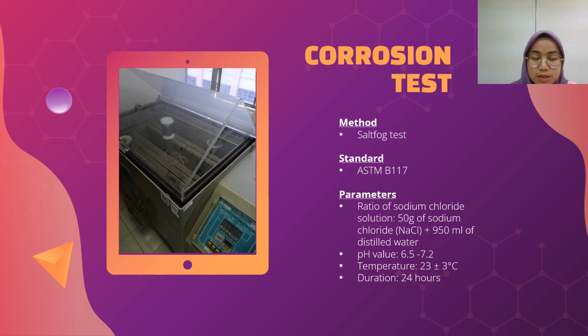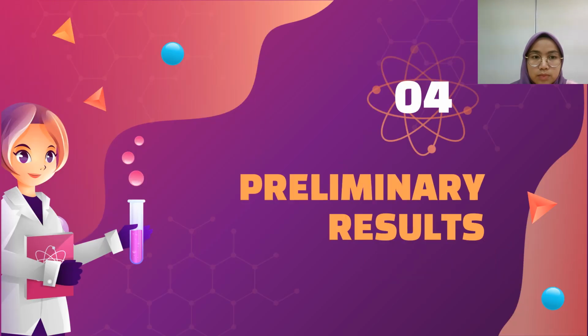For the corrosion test, the salt spray test has been chosen to investigate the corrosion behavior of the sample. The corrosion test will be carried out according to ASTM B117 standard, with the parameters being a sodium chloride solution ratio of 50 g of NaCl plus 950 ml of distilled water. The pH value is 6.5 until 7.2. The temperature is kept at 23 plus minus 3 degrees Celsius, and the duration of the salt spray test will be 24 hours. Last but not least, I'm going to present the preliminary results from this study.